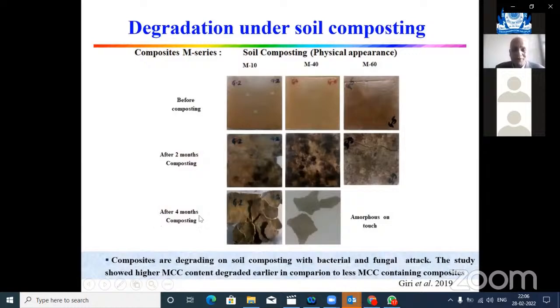And after 4 months, the 60% sample will disappear. We could not find it. So this was the results. So we can see it again, demonstrating that with the filling of the polymer with the microcrystalline cellulose, the degradability of the composites becomes much higher. So the polymer is itself biodegradable, but when we fill it with the biodegradable filler, the biodegradability increases, enhances drastically.